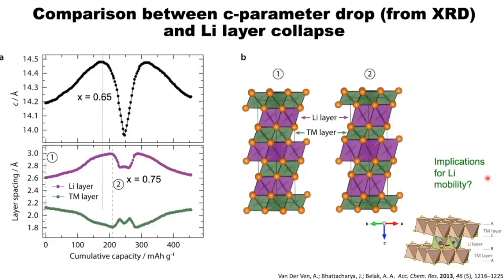So looking at this then, comparing the c parameter drop and the lithium layer collapse, what's interesting is that you see this change in the c parameter at about 0.65, and this dramatic decrease in the c parameter. But if you unpick it and you separate the changes in the layer spacings, be it the lithium layer or the transition metal layer, the key point I want to show you here is that the lithium layer itself doesn't collapse till about x equals 0.75.